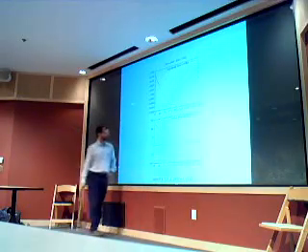It is a function that is continuous for a while and then has sudden drops, and the stress that we calculate is the derivative of this function in the region where it is continuous, and it is meaningless where it has sudden jumps.